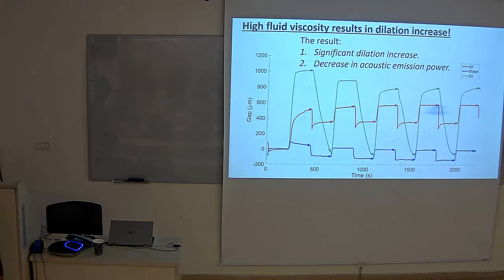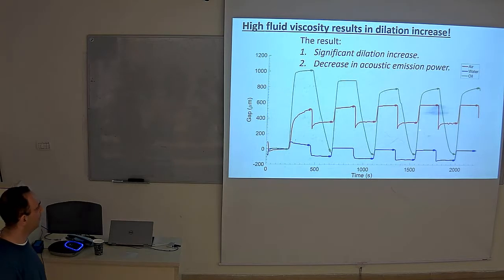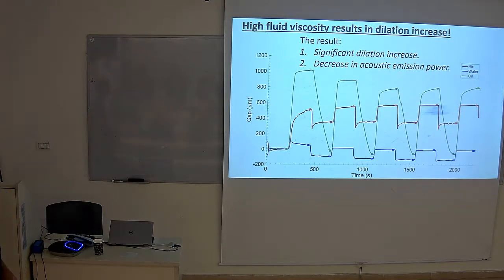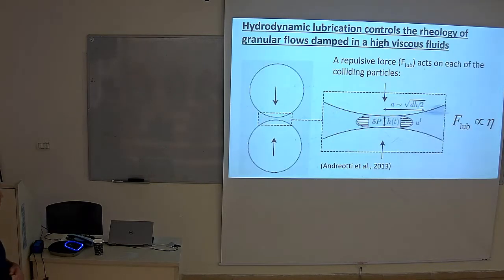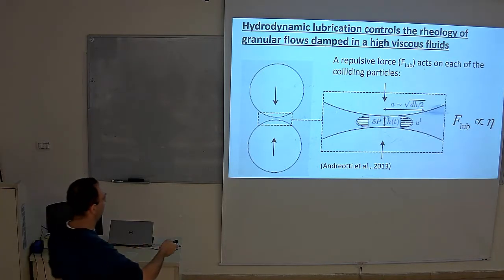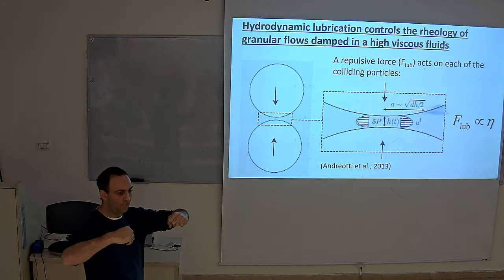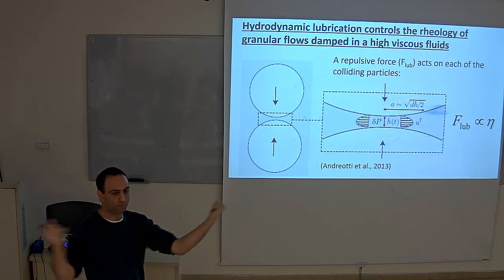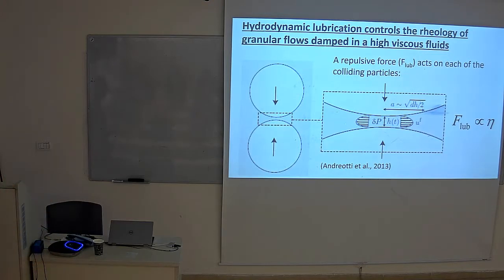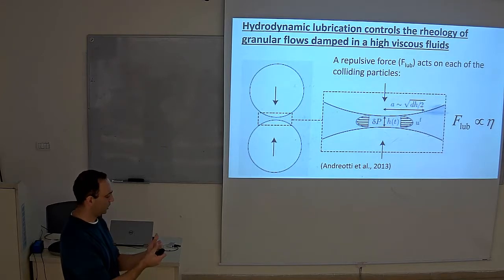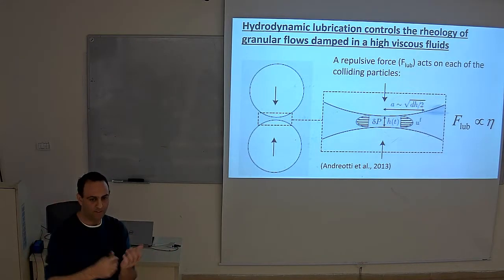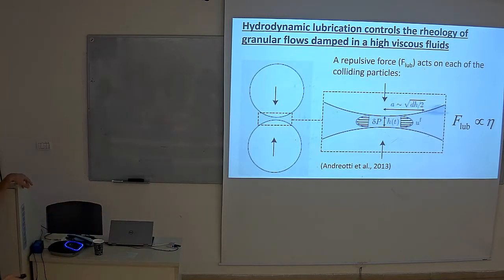However, when we look at the results, we get the opposite. We get something with much higher dilation, even higher than the original dry material. However, there is still a decrease in acoustic emission power, even more than in the water-saturated experiment. So the question is how to explain this, and I think there is an existing theory about hydrodynamic lubrication. When two particles collide in a viscous material, the fluid that is trying to squeeze out is not fast enough to move out, and therefore it's trapped there. The pressure increases in this part, applying a repulsive force on the two grains. That may actually increase the dilation because the energy of these impacts is increased. They are moving more, and they are not losing energy in the impact itself.